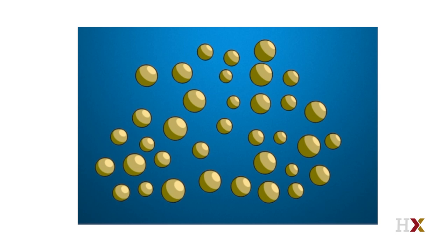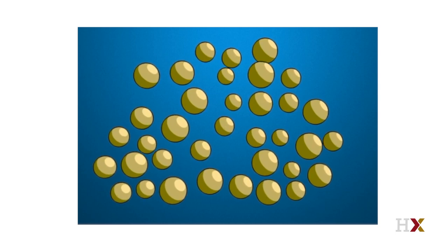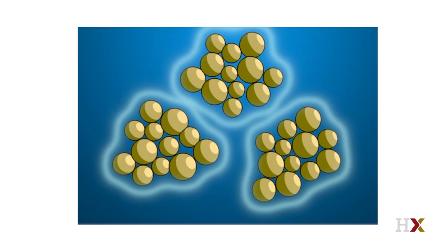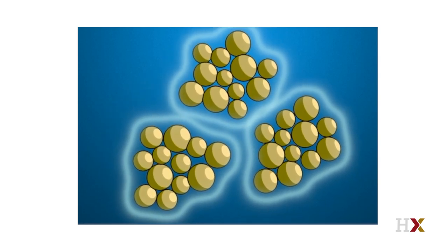We can understand in a simple way why starch is so effective at increasing viscosity. First, the starch granules expand — they absorb water and get larger. As shown in this cartoon, the volume gets larger, so the effective volume fraction of the starch granules increases. While you may start out with only 15% volume fraction, when they've expanded they can occupy a much larger volume fraction. The second way starch increases viscosity is that the granules stick together, forming tenuous structures. The volume of these structures includes the structures themselves plus all the water they enclose, and that's how you can greatly increase viscosity even without having 50% volume of solid particles.